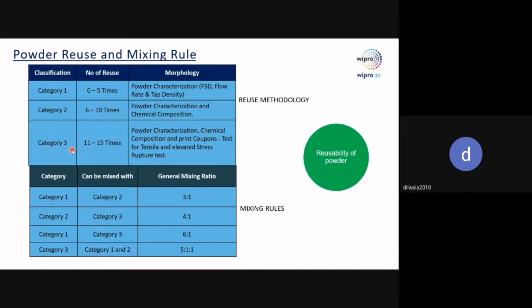Then category 3, which has been used from 11 to 15 times. After the 15th reuse, we do powder characterization, which means all these tests, then chemical composition. We print coupons as well and check the tensile properties and all other structural properties.